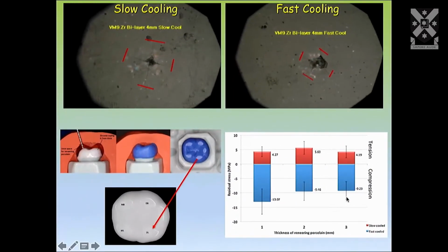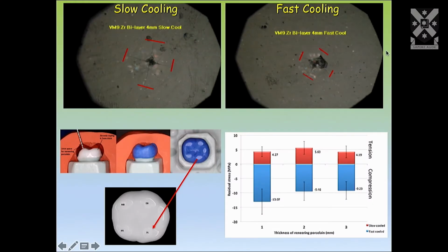And when you have a situation of no residual stress underneath the area you've cracked, the cracks have nothing to inhibit it, so they extend further. But if underneath that area you're indenting, there is compression in the underlying porcelain, it's trying to hold it together. It's a bit like a reinforced windscreen, toughened windscreen. Then the cracks are inhibited from extending. And there's a formula that we then use to convert that to residual stress.